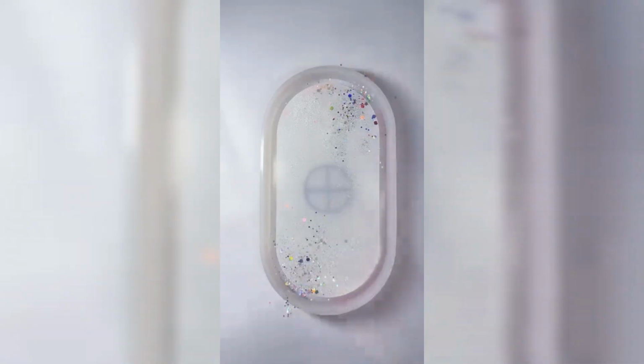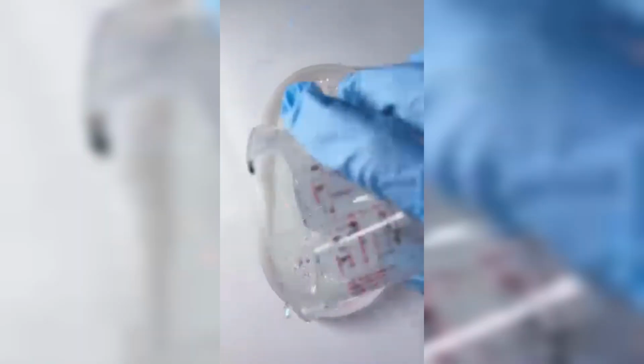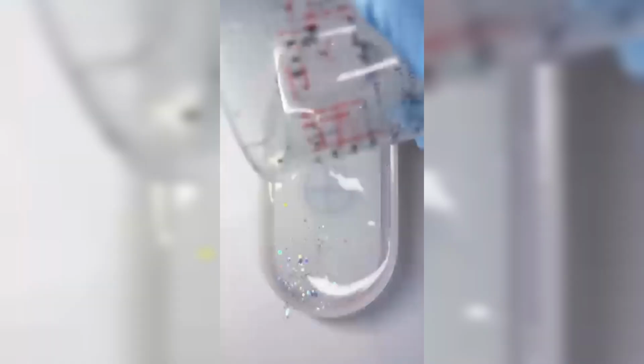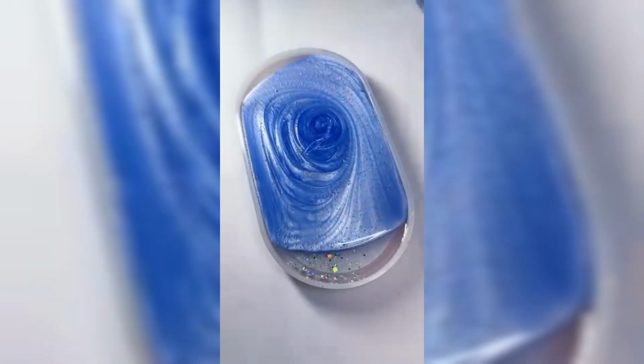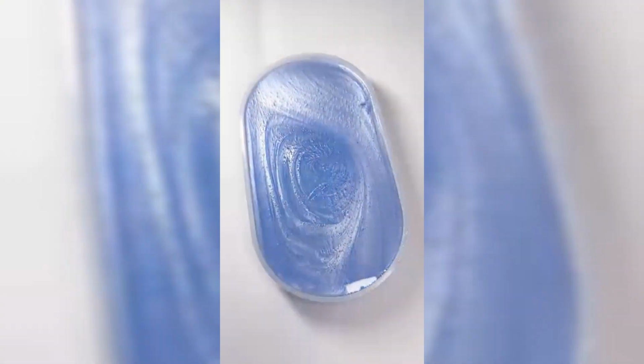Troubleshooting common problems. Tacky or soft spots often mean undermixing, incorrect resin/hardener ratio, or insufficient cure time/temperature. Yellowing may come from low-quality resin, UV exposure, or heat during cure. Choose UV-resistant formulations and avoid excessive exotherm.